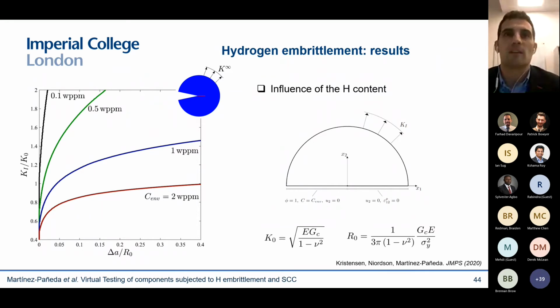What you're showing here is R curves, so crack growth resistance curves. The vertical axis is a measure of applied load versus the crack extension. And you can see here the trend that you will see in experiments. As you increase the hydrogen content, you reduce the fracture resistance of the solid.